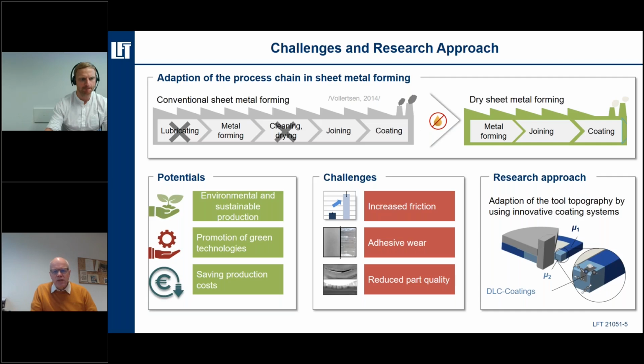Increased friction leads to increased wear, both adhesive and abrasive. And in the process chain we're looking at here, it's mostly the adhesive wear that is a problem. It can also lead to reduced part quality, which was shown on the very first slide, where the sheet thickness was reduced. You might also get damage to the part or even a failing production process. All this means we have to overcome this somehow.